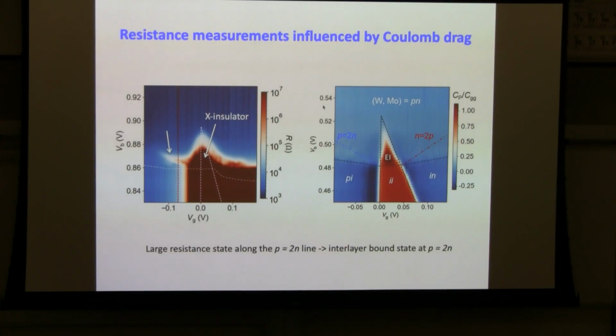And this is the 4-terminal resistance measured with the geometry I just told you as a function of VB and VG in the same range. And you can actually see that in this triangle here, you get a very large resistance, although you have electron-hole pairs. The reason is that there is an electron-hole bound state, so you get an insulating state, and that's an excitonic insulator I've been just telling you.